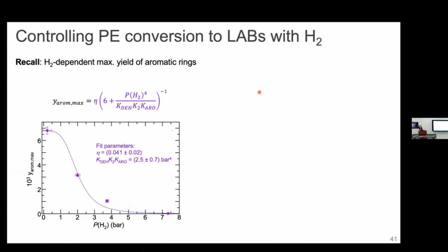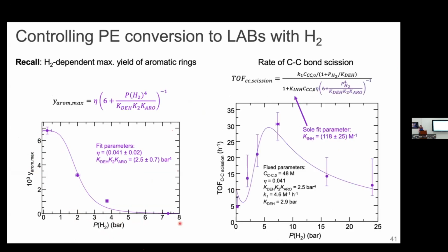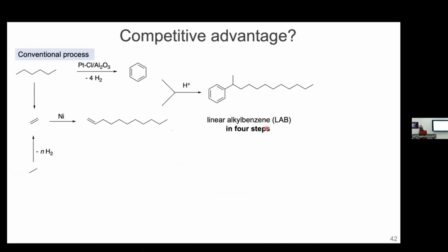We can tune the chemistry, and this is what my group gets really excited about doing. We can look at the effect of the hydrogen pressure in the reactor in terms of what comes out. This is the yield of aromatics, which decreases as you increase the amount of hydrogen. But interestingly, in terms of the rate, this is the turnover frequency. The rate is a maximum at some low pressure of hydrogen because the hydrogen is cutting the long chains into smaller chains, and then the catalyst is causing them to aromatize. So we have the conditions now to do this reaction very efficiently.